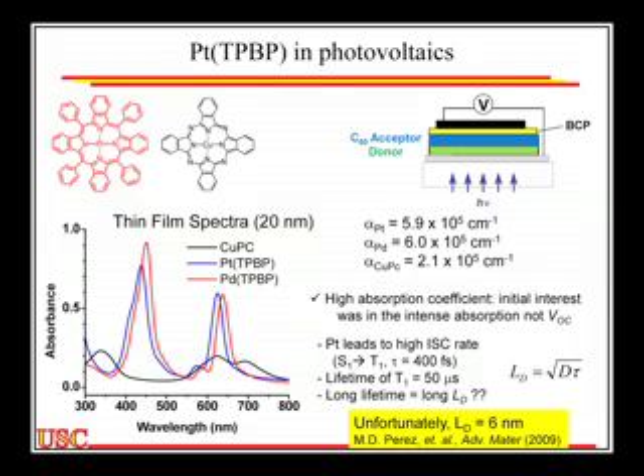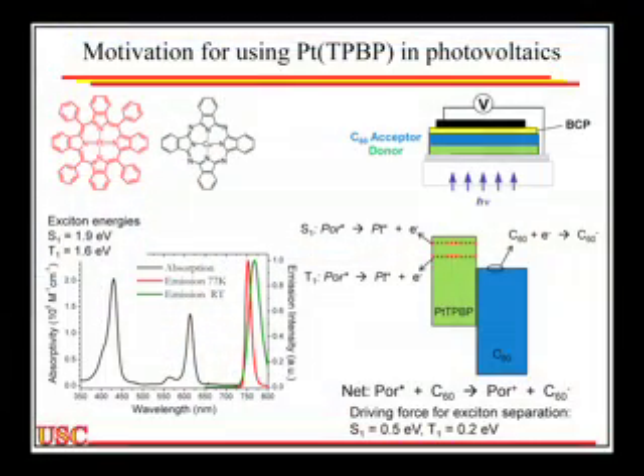So first of all, let me go back, but we did make devices with this. And so the first question that comes to mind is it's a triplet. And in organic LEDs, we were happy with triplets because their energy is low and they don't get lost. They have long lifetimes, and you don't get a lot of quenching due to energy transfer to alternate sites because the energy of the triplet is so low. So the question is, what if the energy of the triplet is so low that this exciton no longer has enough energy to be able to charge separate at the donor-acceptor interface?